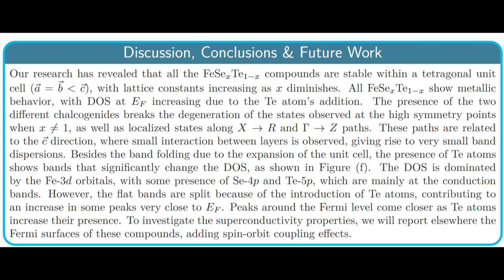The presence of 2 different chalcogenides breaks the degeneracy of states observed at the high symmetry points when X is different from 1, as well as localized states along XR and gamma-Z paths. These paths are related to the Z direction, where a small interaction between layers is observed, giving rise to very small band dispersions. Besides the band folding due to the expansion of the unit cell, the presence of the tellurium atoms shows bands that significantly change the density of states as shown in figure F.